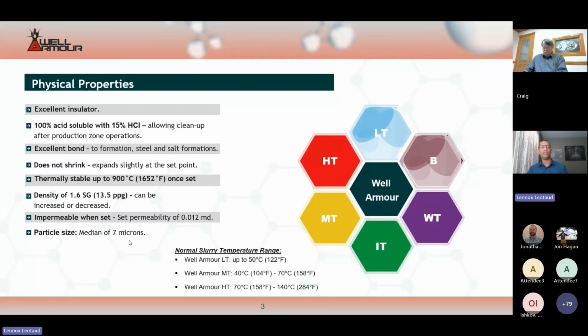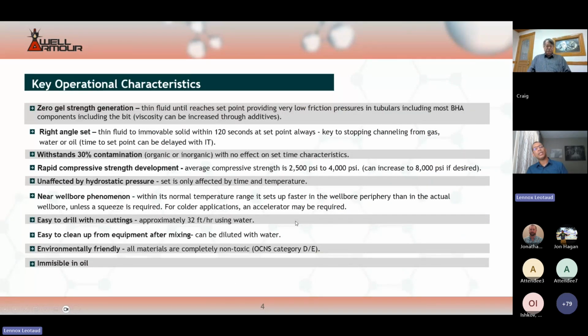That being said, unlike, say, a cement slurry, if you were to use the Well Armour slurry in a tight formation, or you're looking to squeeze it into a very, very narrow channel, even if you were to screen out the particulate fraction of the Well Armour slurry, the filtrate will still set. So that's a big difference, or a big performance property of the Well Armour as compared to, say, a cement slurry. Listed on this slide are the key performance characteristics of the Well Armour system. And the primary characteristic of the Well Armour is that it has zero gel strength generation.